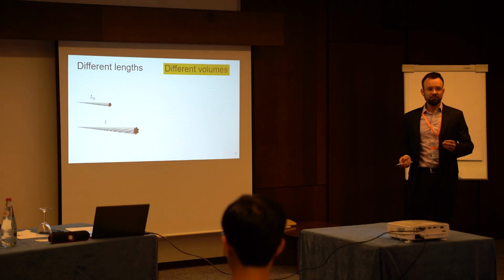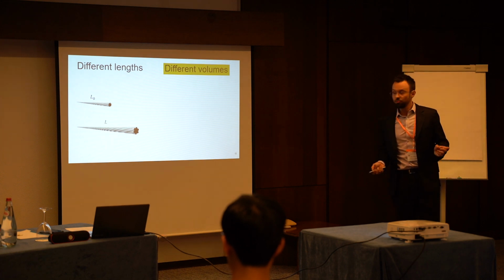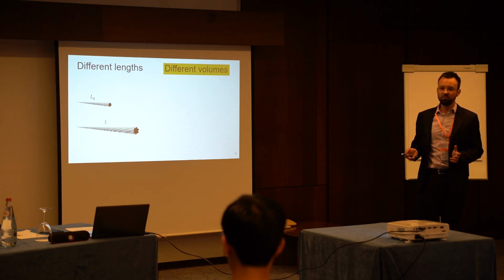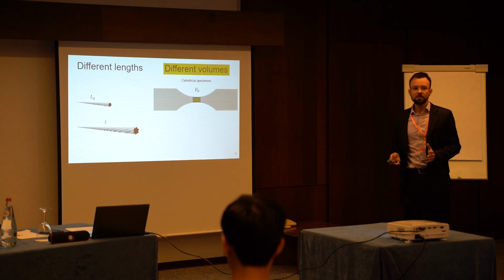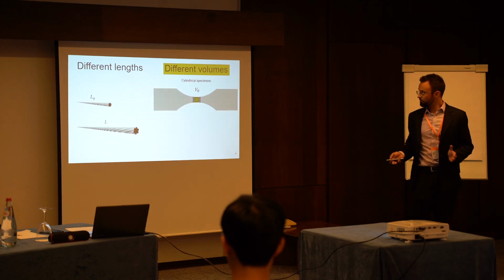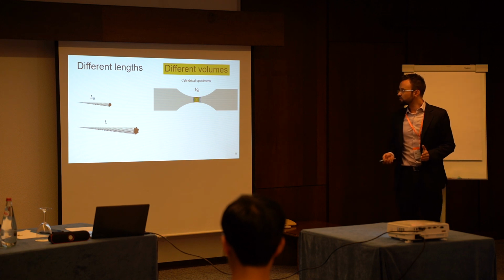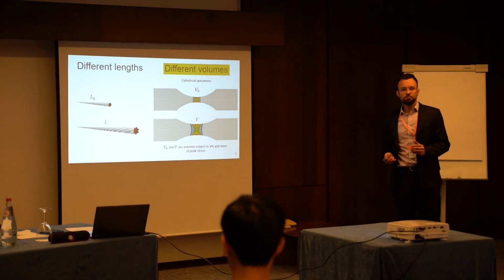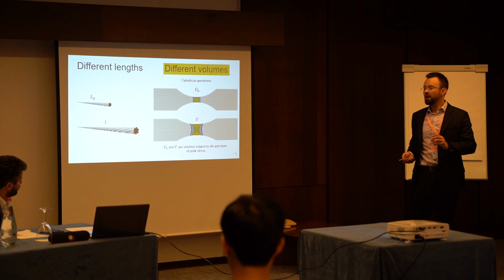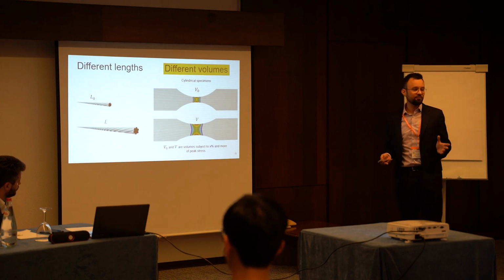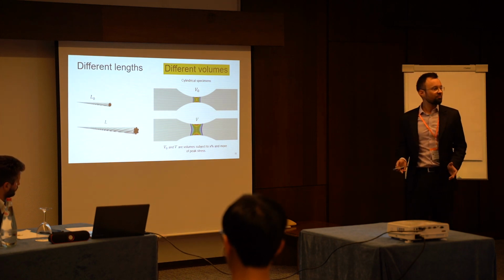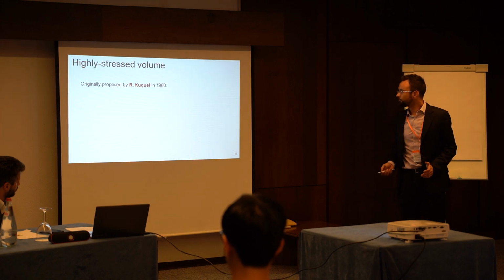Not only are fatigue models for different lengths available in the literature, but also for different volumes. It's based on highly stressed volume theory, and these volumes are subject to a fraction, for example, 95% and more of peak stress.